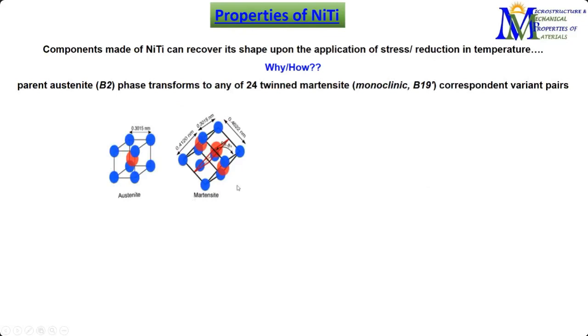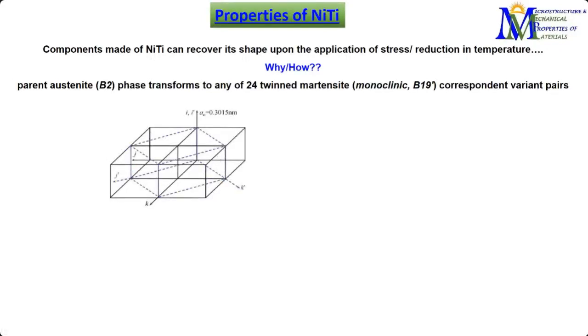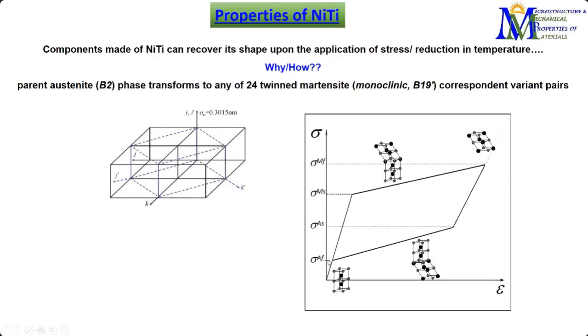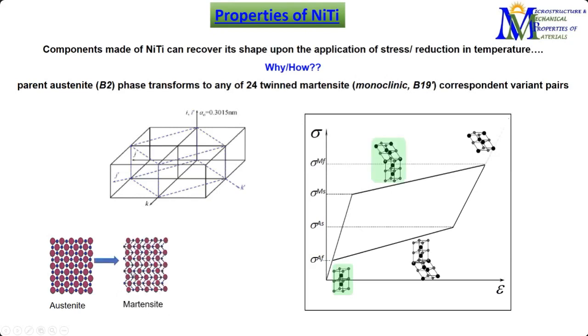This is different, completely different from the martensite we have just seen in case of titanium or what we regularly see in case of steel. This has two different crystal structures that can be achieved by applying stress or temperature. If we have the initial structure as austenite, which has a cubic structure, and we apply stress to it, it transforms to martensite, which has a monoclinic structure. Afterwards, if you keep adding stress, there is a huge amount of strain generated, but only a minor amount of stress is required, and it basically does a detwinning of the martensite. Initially it forms a twinned martensite and gets stretched out, forming detwinned martensite if we keep adding stress, and we get a large amount of strain.